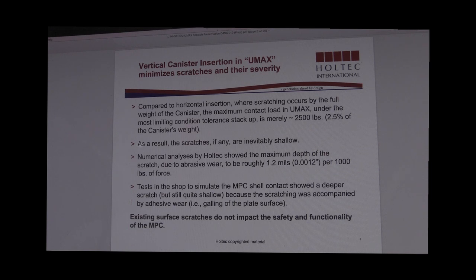specific to the MPC inside the UMAX, by our calculations, the depth of the scratch due to abrasive wear is on the order of 1.2 mils, or 0.0012 inches per 1,000 pounds of force. So even if the maximum contact force is as much as 2,500 pounds, you multiply that by 2.5, we're still talking about scratches due to abrasive wear that are on the order of 2 to 3 mils in depth.